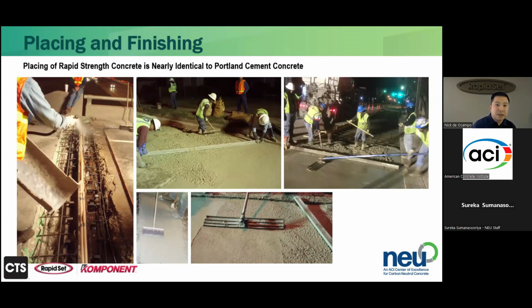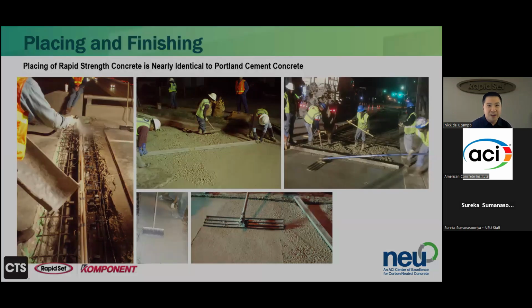I do want to stress that for the placing and finishing of rapid set concrete, especially if you're in an overnight closure, the placing and finishing of rapid set cement is nearly identical to that of Portland cement. You use the same consolidation methods, screeds, floats, anything you would on a traditional Portland cement job site. However, there is one very important caveat.